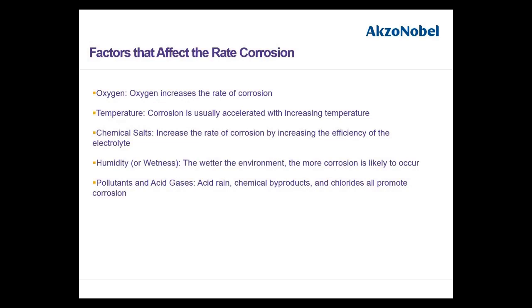Factors that affect corrosion, I was telling you: oxygen. Higher the oxygen, higher is the rate of corrosion. Keep in mind, temperature, it gets accelerated because of increasing temperature. You heat it up, the rate of corrosion increases. Chemical salts, because they can form electrolytes, will accelerate the rate of corrosion. For example, pure water, distilled deionized water, you immerse an iron nail, it will not corrode easily. But you add a little bit of sodium chloride or salt inside, it will corrode very fast.